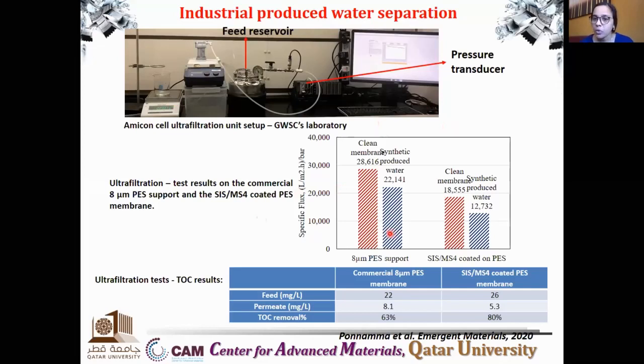Here they also noticed that the TOC removal percentage of the SIS mesoporous silica composite coated on the PES substrate was much higher. I told you that we handed over the membranes, but we did some kind of coating process for these membranes. There is a standard membrane called polyether sulfone, and we did the electrospinning of styrene isoprene styrene mesoporous silica composite on top of this PES membrane. So we don't need to make the electrospun fiber so thick. It's just like a surface modification of PES membranes.